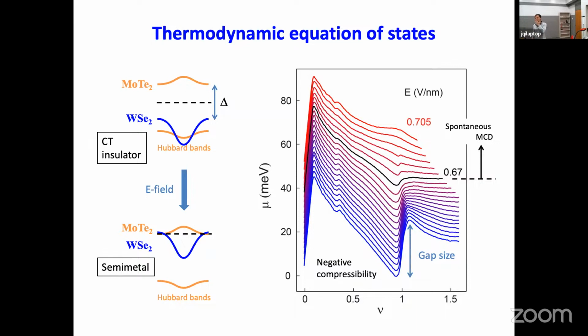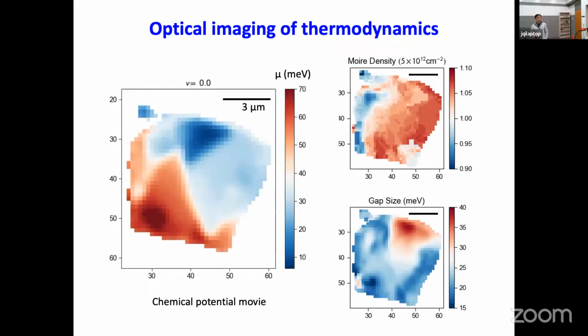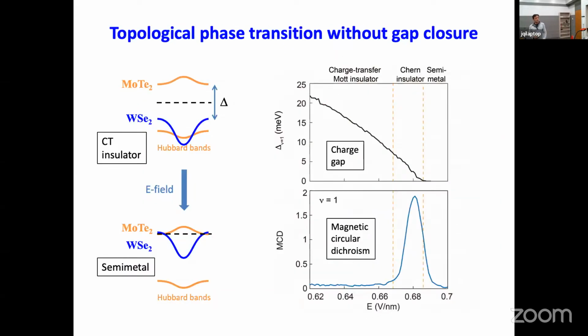And the reason we choose monolayer tungsten selenide is just because that step edge is very sharp, and it really just improves our sensitivity on the chemical potential sensing. In fact, it works really well, that the noise of the chemical potential measurement is about 20 microvolt per root hertz, even for DC measurement. So it's actually a really sensitive chemical potential sensing method.